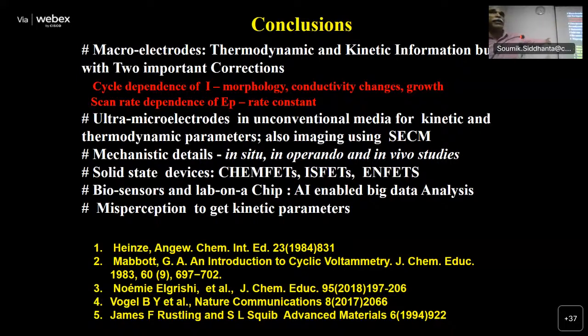Macroelectrodes and microelectrodes, so much of a difference. Thermodynamic and kinetic information can be obtained. Cycle dependence, I did not talk much. 1, 2, 3 cycles, you can do cycle dependence. 200, 300, 500 cycles can be done to look at the durability of an electrocatalyst. Morphology, conductivity changes, growth, scan rate dependence, all that can be investigated. Ultramicroelectrodes allow you to work in unconventional media, ionic liquids, microemulsions, not very conducting in terms of ionic conductivity, but you can still do it. In microemulsions, the CMC, the critical micellar concentration of surfactants, can also be detected by using voltammetry with external redox probes. Interestingly, all solid state measurements are also possible.